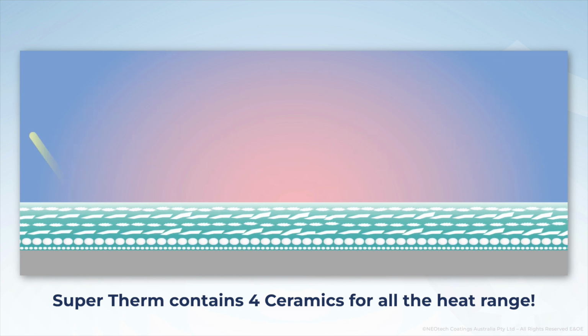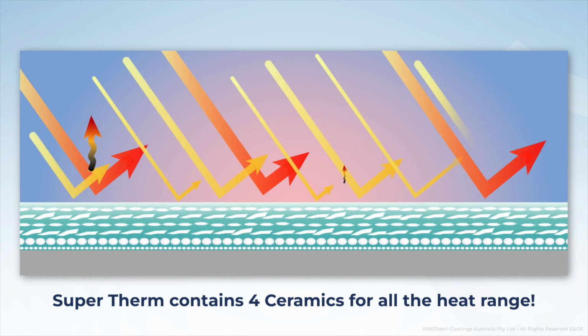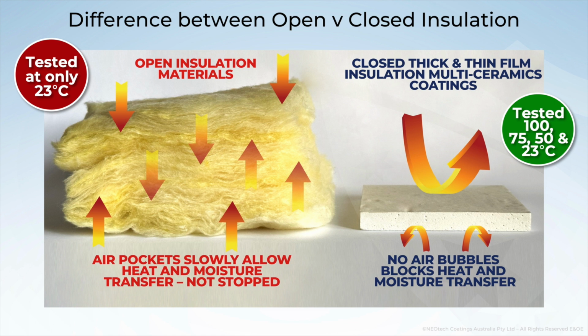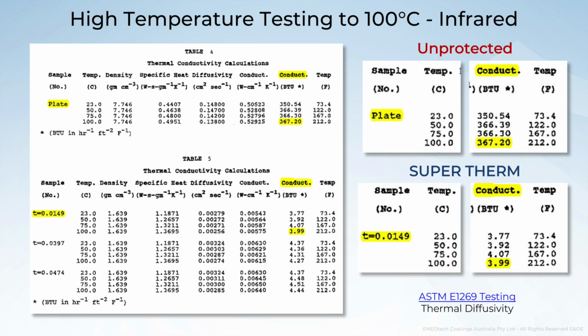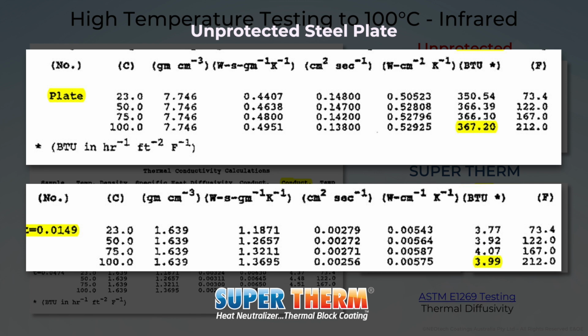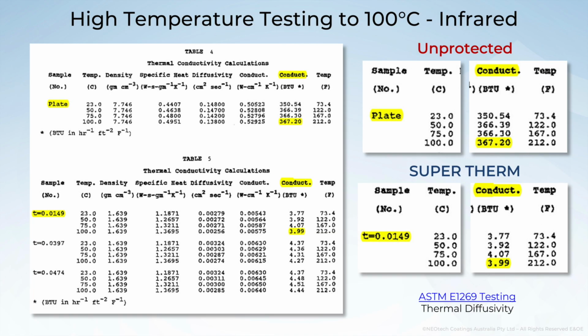So while traditional insulation, including aerogels, are only tested around 23 degrees, that doesn't give you any real indication because it's not tested in the field, it's not tested with moisture, it's not tested with dust, it's not tested with compression. We've been tested at 100, 75, 50 and 23 degrees and performed the same the whole time. And this has major benefits.